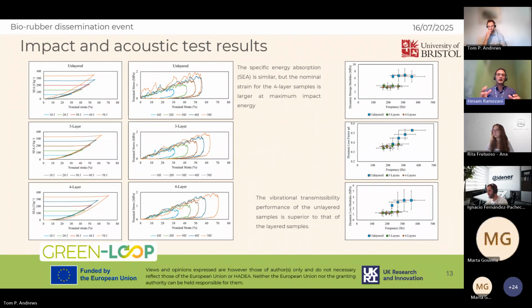And as you can see, the 4-layered sample shows a higher capacity for absorbing the energy and for dissipating it through different mechanisms. And we also see that for the unlayered sample, after the 40 joules, the nominal strain is limited to nearly 50%, while for the 3-layered it is 60%, and the 4-layer is nearly 70%, which shows that the multi-layer samples are more compliant. And they can be used in the applications that need compliant materials.